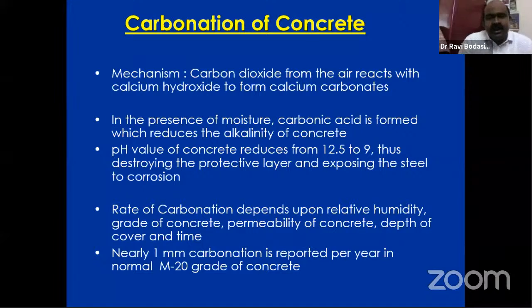So then coming to the next major factor affecting concrete structures, which disturbs the durability of the structure. The carbon dioxide from the air reacts with the calcium hydroxide to form calcium carbonate. In the presence of moisture, an acid is formed which reduces the alkalinity of the concrete. The pH value of concrete is generally 12.5 and above, and when it comes down from 12.5 to 9, it immediately affects the protective layer of the steel. So the carbonation action immediately starts and it deteriorates the steel.